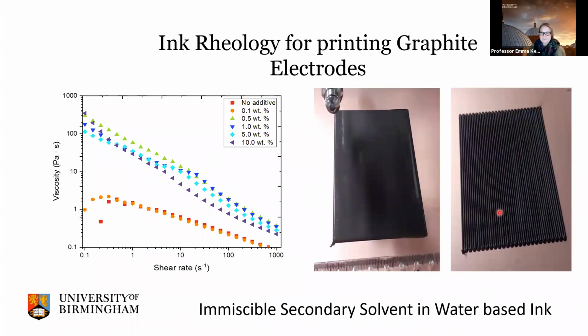And in order to do that, what we did was add a secondary solvent into the inks to try and control the rheology better. This immiscible secondary solvent we used was a fatty alcohol, octanol. The red and the orange that you see here is no additive and a small amount of 0.1 weight% in water going in. As soon as we upped it to 0.5%, you can see the rheology properties changed quite significantly.